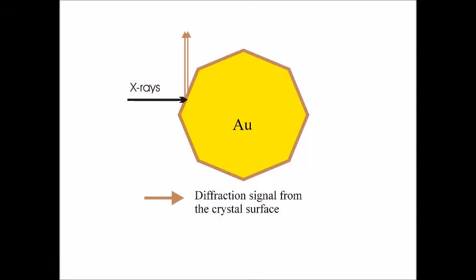To look at the crystallinity of materials, the standard methodology is X-ray diffraction. However, because gold is so dense, X-rays only penetrate the very surface. And if we want to look at the interior, we would typically have to cut samples like this open. However, because of the great value of specimens like the ram's horn, we can't do that. Instead, we had to turn to a different technique.